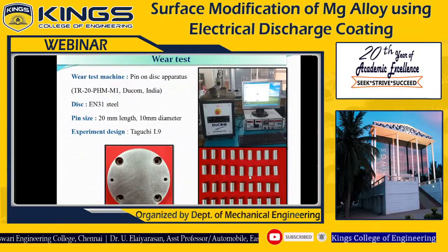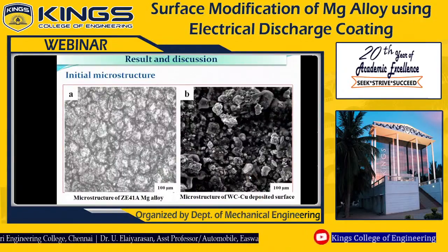Then, result and discussion. It's a very important topic. The initial microstructure has been given for the ZE41A magnesium alloy and the tungsten carbide copper deposited surfaces. In this ZE41A magnesium alloy, a uniform distribution can be seen in the microstructure. Here is the microstructure of the tungsten carbide copper deposited surface.